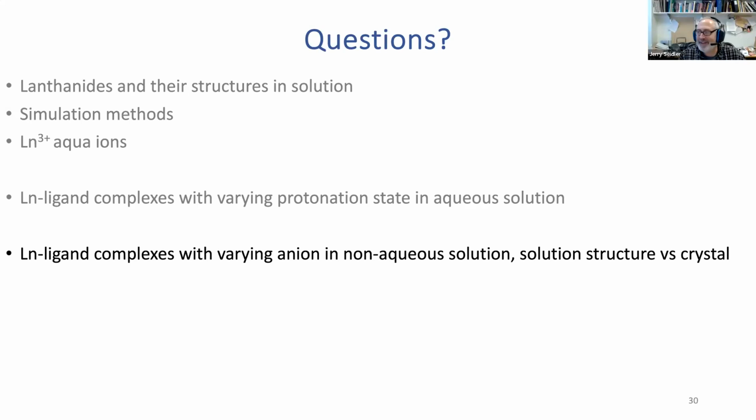And then we have a follow-up from Anatoly. Just a very quick comment to Fernando's question, and also to the comparison with possible fits. It's important because this method proves very powerful if the distribution that you obtain is very anharmonic, asymmetric, and cannot be probed by using any kind of cumulants, because this series may not converge too fast.